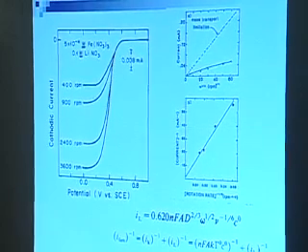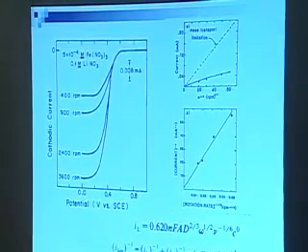Well, qualitatively, this is what Marcus is telling us is supposed to happen. As the redox potentials between the iron and the ferrocyanide get further apart, the rate should go up. Right? That's this cross relationship that I've been talking about. You can't easily get the data out of those cyclic voltammograms or linear sweep voltammograms, so we went to the rotating disk experiment. So here's rotating disk voltammetry.